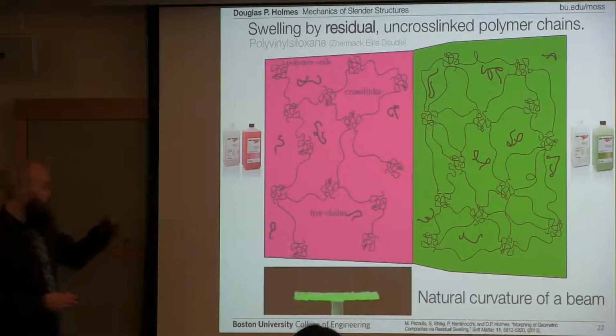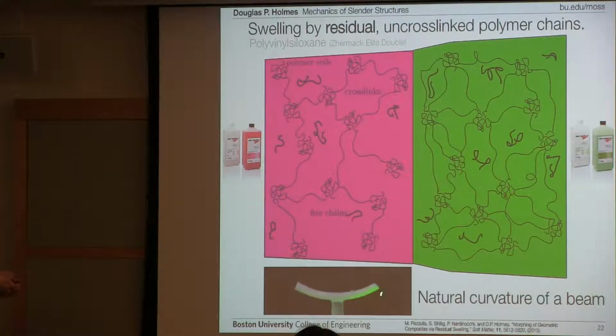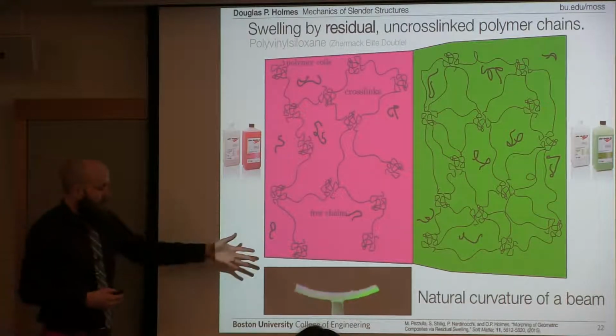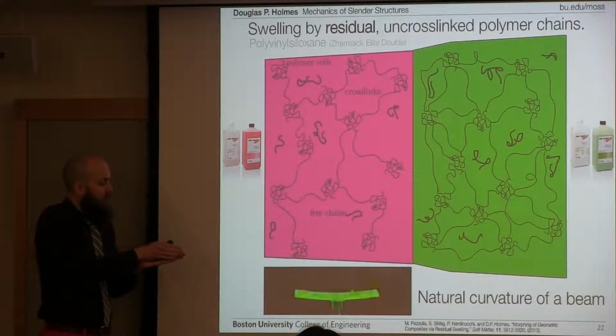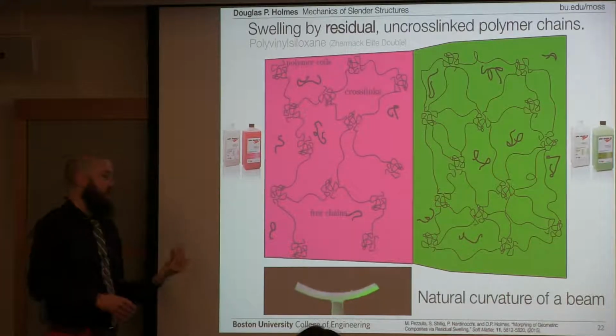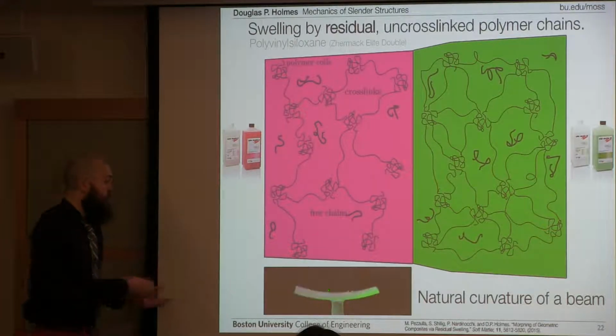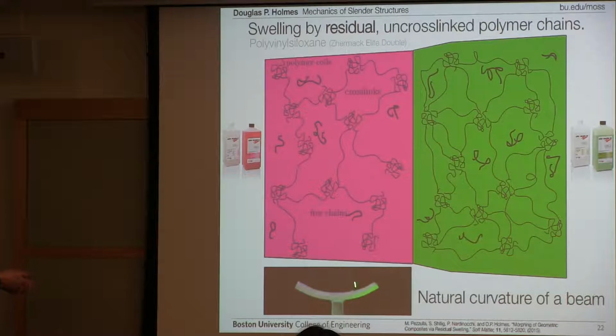And so what we do is we make a thin beam. You can't really tell, but the bottom half of this beam is green. The top half of this beam is pink. We basically form a bilayer of this green and pink material, and we watch how this curvature evolves as a function of time. And this is our way of inducing a curvature into a soft material.